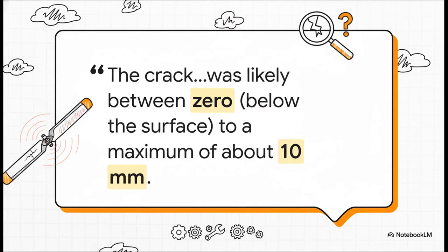The investigation into the 2011 Canada crash gave a definitive answer: nope, not at all. Get this, the blades on that helicopter had gone through 16 of these wipe checks. The very last one was done just 41 flights before the crash. But the analysis showed that at the time of that final check, the crack was either still totally inside the blade or at most 10 millimeters long on the surface, way too small to be seen reliably. The test had failed, and the consequences were fatal.